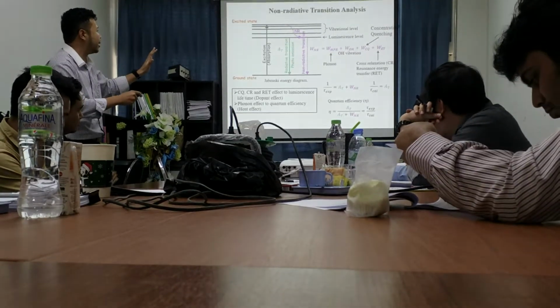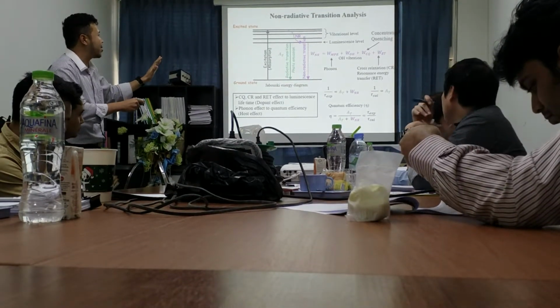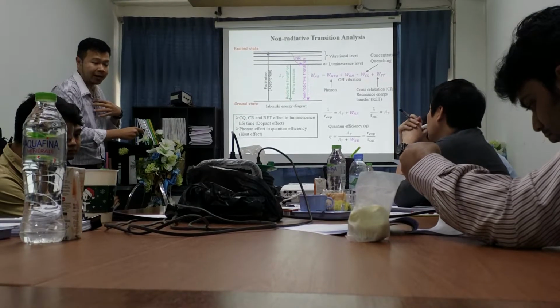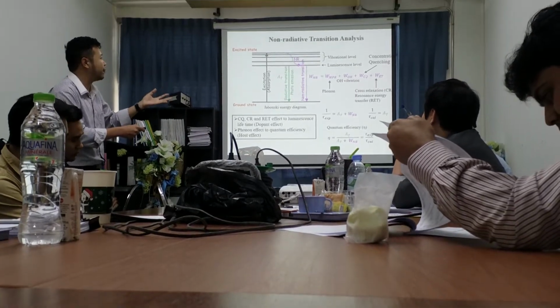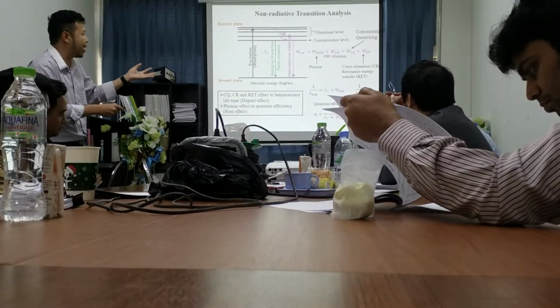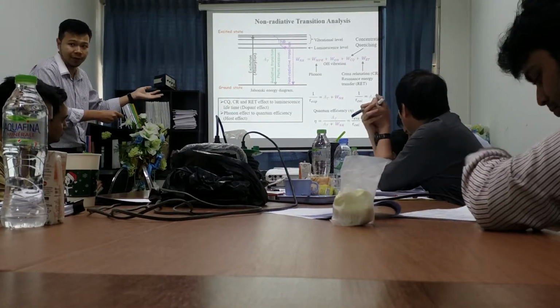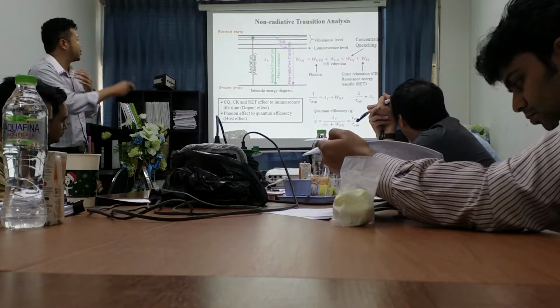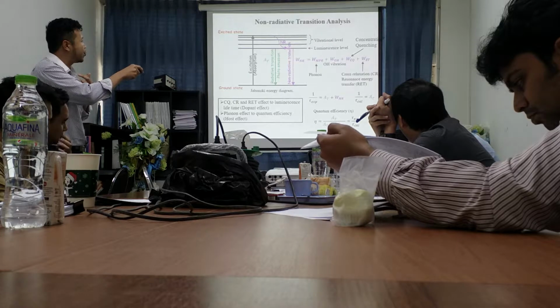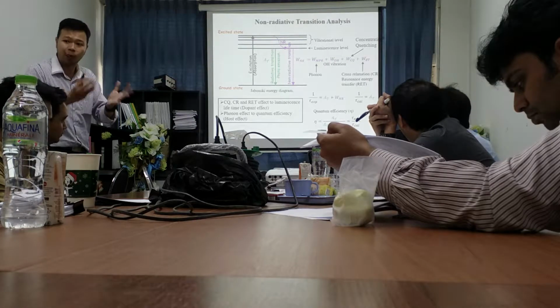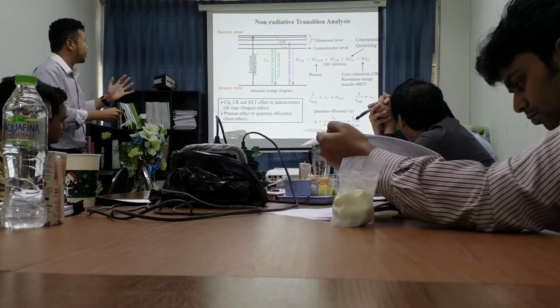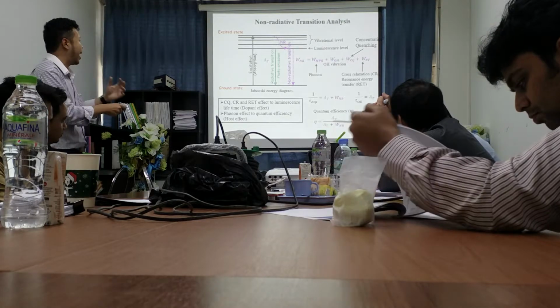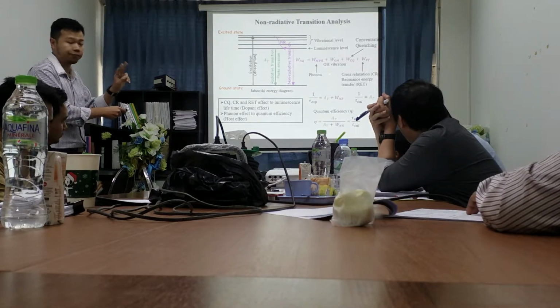It means this transition gives us the phonon vibration, the OH vibration, the concentration quenching, and the cross relaxation and energy transfer. We like this one. We don't like this one, because this one gives us the strong luminescence. However, our glass has both transitions.